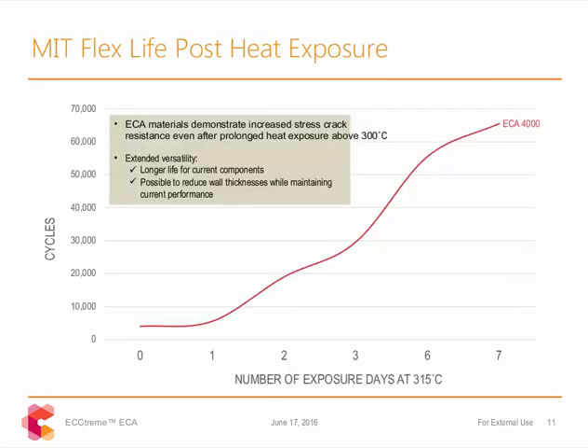Interestingly enough, also unique to ECA is that typically an increase in crystallinity can lead to brittle or rigid material that can be prone to stress cracking. ECA actually, when exposed to heat, the MIT flex life of the material improves over time. Here is an example in ECA 4000, which demonstrates over 1,000% increase in flex life after 7 days of 315 degrees C heat exposure. And what does this mean in an application? It means longer life for components, and it means the possibility in wire and cable applications to reduce wall thickness while maintaining performance.